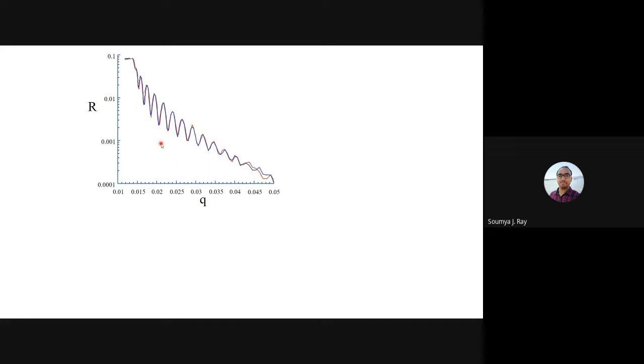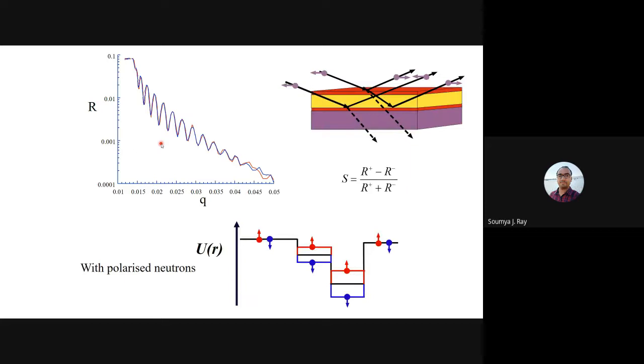So here the question comes: if I'm getting a similar thing, then why do I need to do this? Because neutrons are more expensive to get, and secondly they usually have lesser intensity compared to the X-ray ones. So why is it done? The reason is that, in addition to simple reflectivity, the thickness and roughness, you can also get information about the magnetic texture. Since neutrons are magnetic in nature, if there is a magnetic layer, then a non-magnetic layer, and then another magnetic layer, the magnetic environment across the depth will be different.